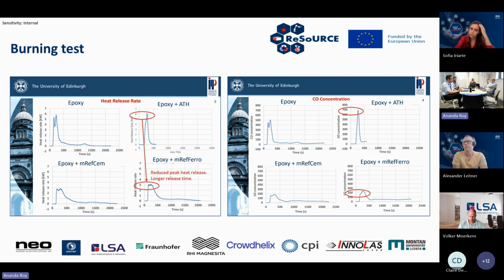And you can see the amount of CO and CO2 released within the mRefCem and MREF-Ferro is much lower. So such behavior is quite advantageous within construction materials, helping to delay that spread, which is critical for evacuation and firefighting. Also, the fact that the harmful gases released within the burning system are reduced is very advantageous.